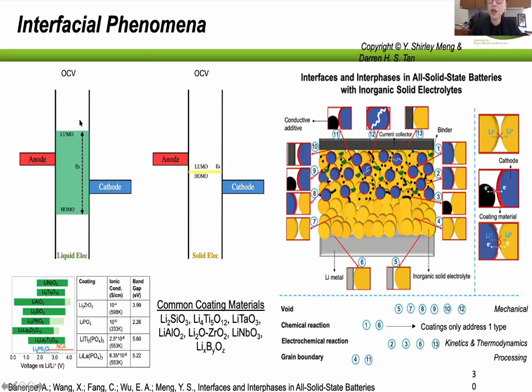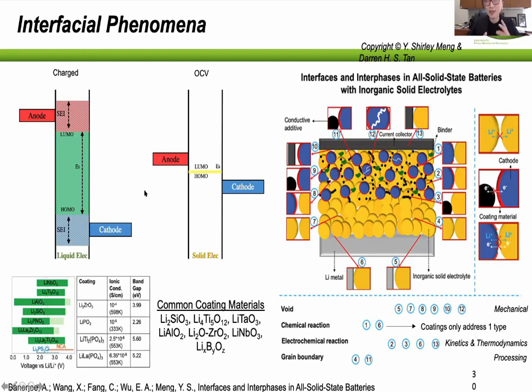Okay, interfacial phenomena. In liquid, the cathode and the anode are both chemically stable in the liquid electrolyte. You see the HOMO-LUMO gap is so wide, and because we're using intercalation chemistry, right? So the anode is quite stable, the cathode is quite stable, and then you actually form SEI. This is well established in our field. Now you start using solid, and the worst case is the solid that we want to do is lithium metal. And bad news, lithium metal reacts with everything, right? Even if it's a polymer, if it's a sulfide, they react. The only two solid electrolytes that are stable with lithium are LLZO and LiPON, right? So you actually have a chemical stability problem.